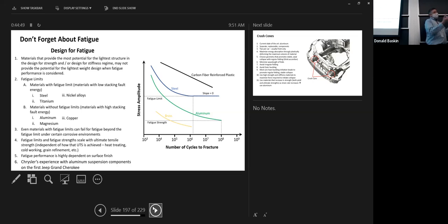With time, cycling, these cracks propagate a little bit, a couple microns at a time. And eventually you've got so much of the cross section that has a big crack in it that this A is actually way smaller, but the F hasn't changed. And at that point, when you hit that threshold, the crack just propagates through the whole cross section.